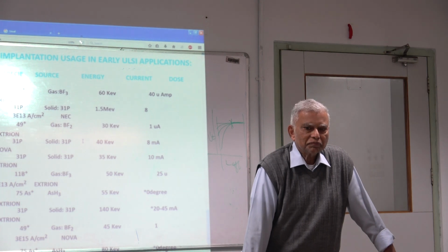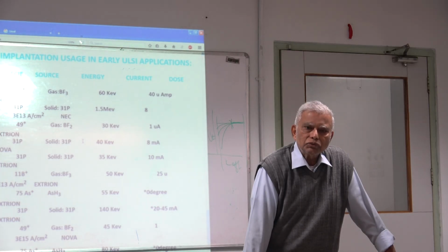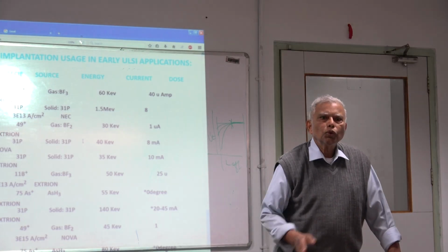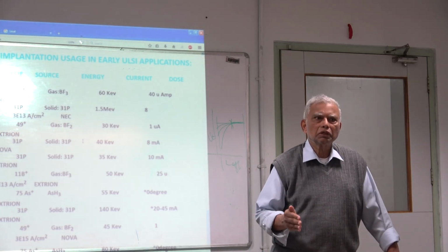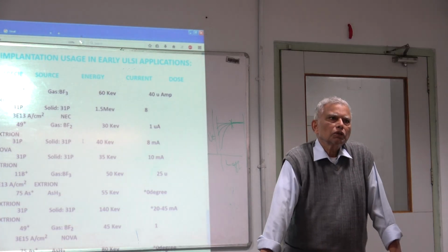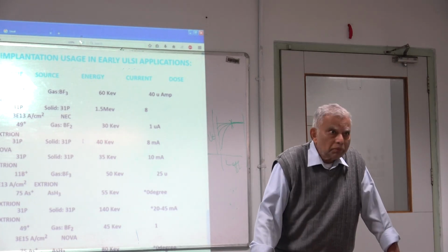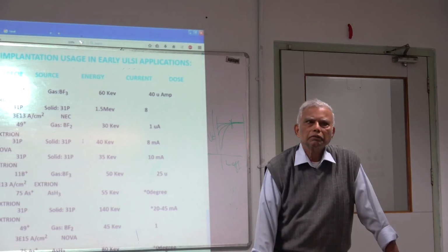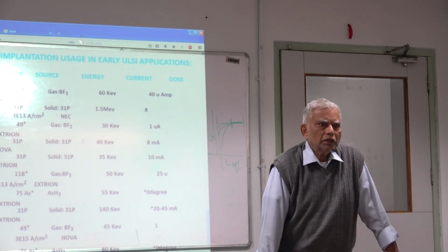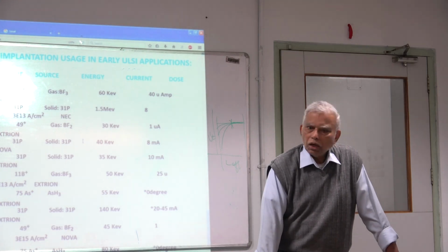We succeeded, not to the ideal way we want. There's nothing ideal in this world. But we learned a lot. And now some of the tricks we played off of is that we will hold off that particular thermal treatment towards as late as possible so that we use the total amount of thermal energy to the least extent. So we had to carefully assess how much temperature we are putting in where and why. The problem comes in is that when you do a certain implant, you create damages. You have to activate the impurities. The impurities are not activated at that point. So how do you know what you have done?